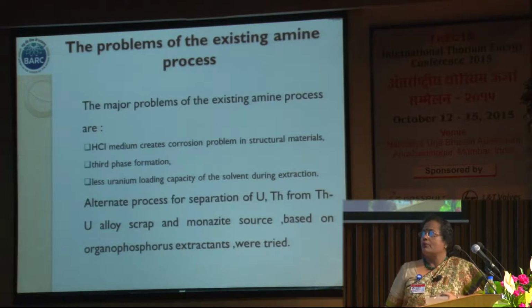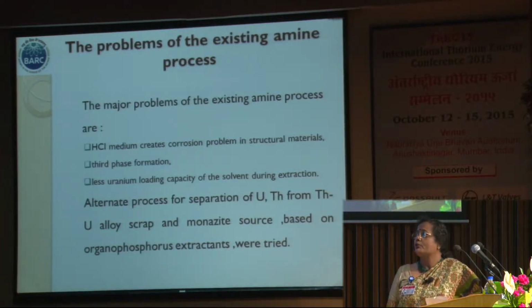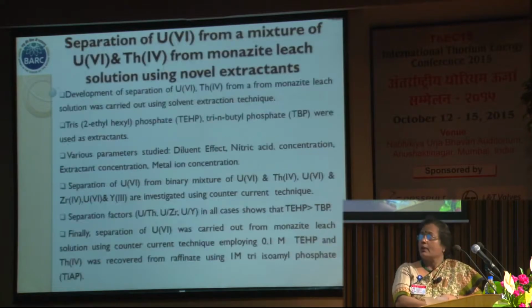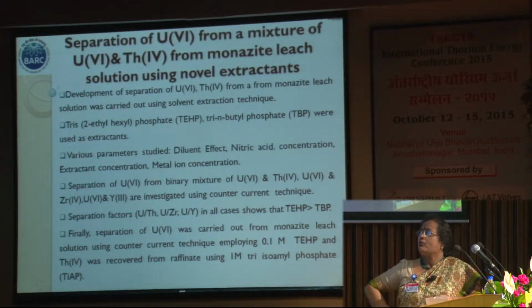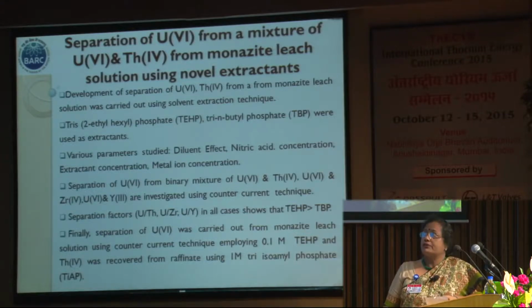So based on all these problems, we thought of generating an alternate process for separation of uranium and thorium from thorium-uranium scrap alloy, and then we extended it to the monazite source based on organophosphorus extractant, as I said, developed by our Heavy Water Board. Two novel extractants were tried. One is tri-2-ethyl hexyl phosphate, another was triisoamyl phosphate. What we did was check the efficiency of the first, tri-2-ethyl hexyl phosphate, with thorium uranium metal scrap to see how much separation factor we can get, and then it was extended to the monazite separation.